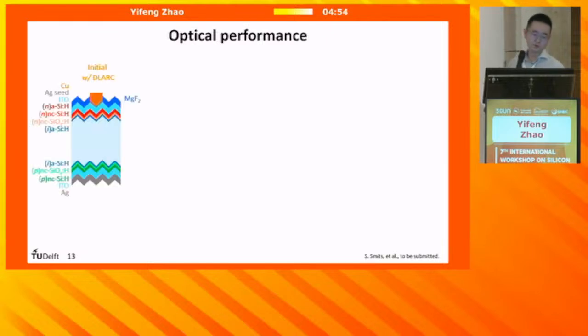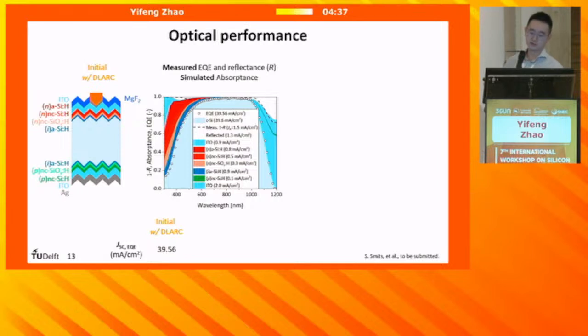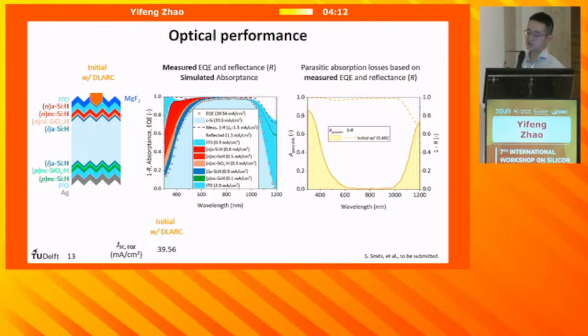Let's start with a traditional full area TCO and full area doped layer solar cell with an additional anti-reflection layer, MgF2. We look at optical performance only at the unshaded areas. Here we show the measured EQE and the reflectance, shown as the white dots and the dashed line in the plot. To understand the optical loss of this device, we also performed optical simulation. With this conventional heterojunction cell design, we have a JSC from EQE of 39.56 milliampere per square centimeter. Further, based on the EQE and the reflectance, we also plotted the parasitic absorption losses, highlighted by the shaded area.